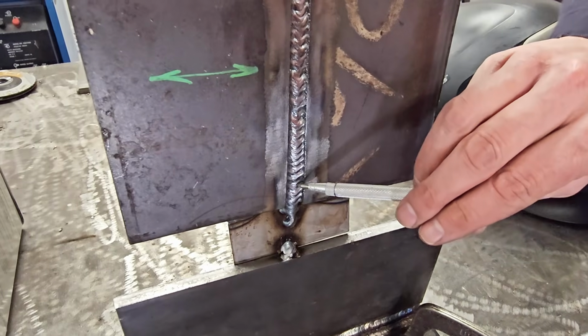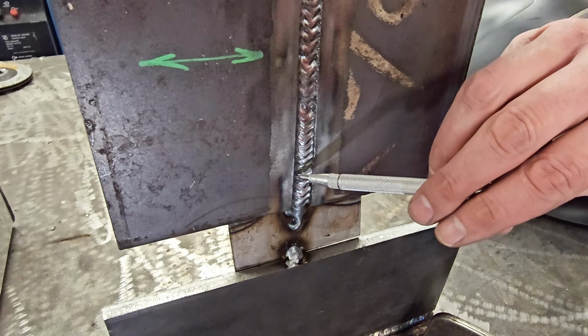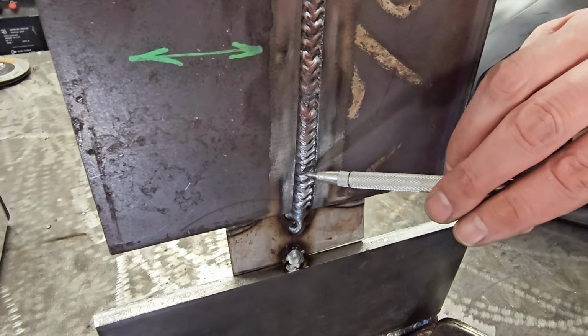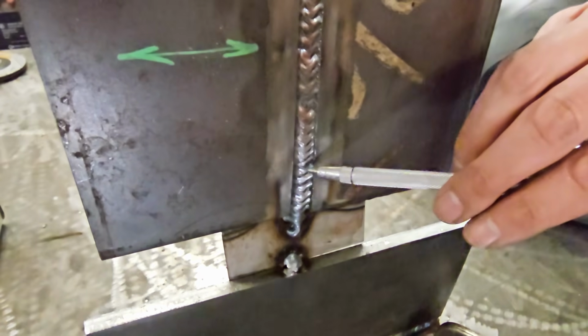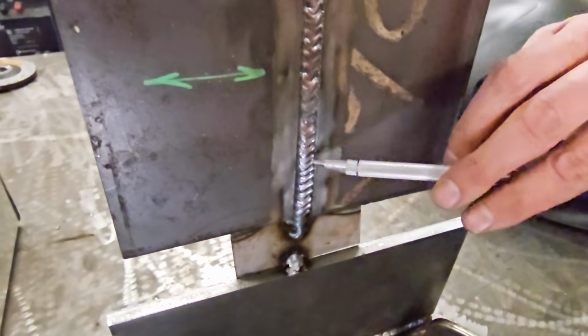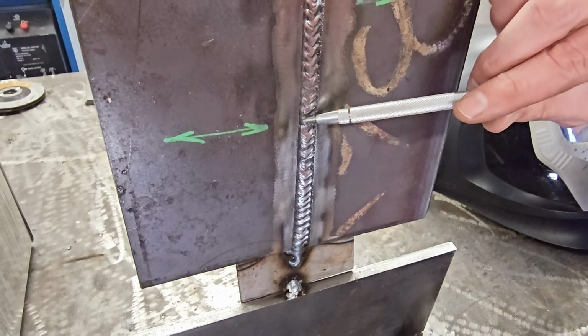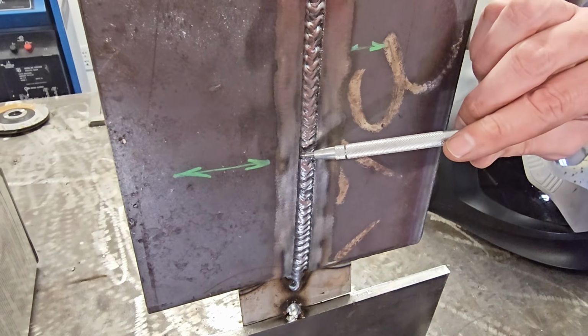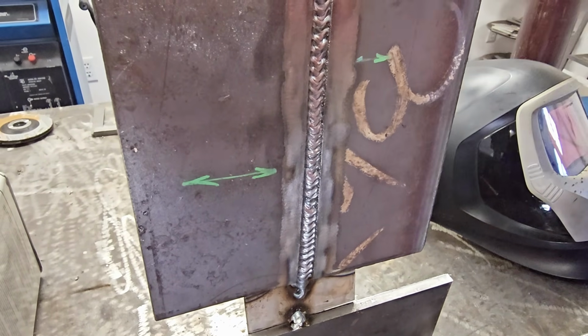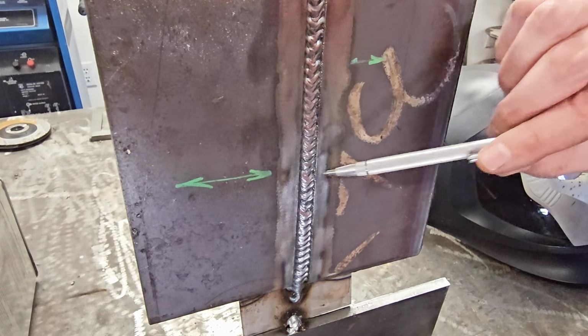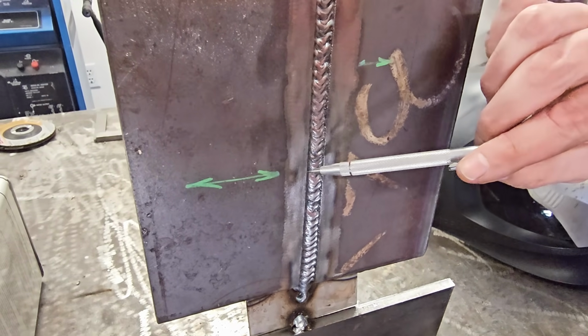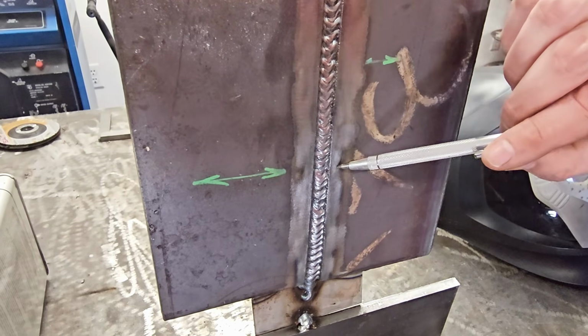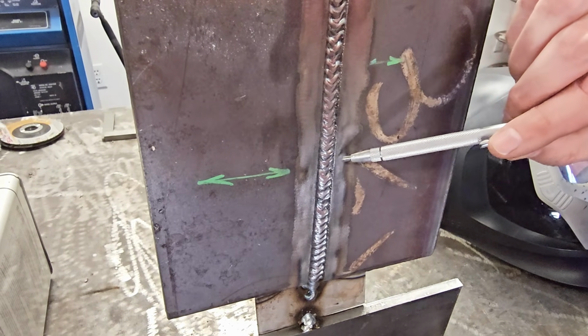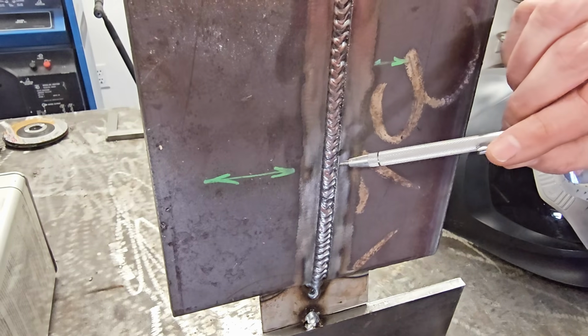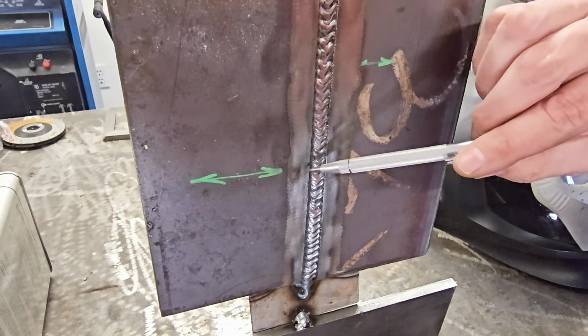All right, so for my fill pass, we want to make sure we're using this Z-weave pattern and we're pausing on the edges and letting it fill up so that we have a nice flat layer in there. We want to leave about a dime's thickness left over to the edge of the bevel for our cover pass. If we get the proper stack up of each one of these layers, it'll make it a lot easier to get a cap pass which is nice and smooth, that's not too high over the 1/8 inch maximum, and won't have any underfill in the center.